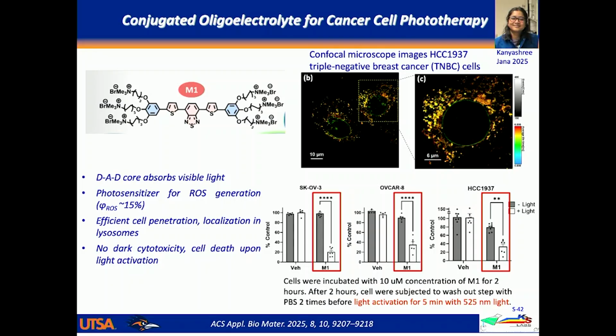So quite clearly the dye does go into the membrane. The different colors represent different lifetimes, by the way. This is a lifetime image. And it turns out green is a little bit of a shorter lifetime than the orange and yellow that we see when the molecule is in the lysosomes. But quite interestingly, if you then take those cancer cells and you expose them to light, just 5 minutes of green light, we can see pretty substantial killing effect. We can reduce the efficacy of the cells by about 80% under the conditions of the experiment that's shown here. These are 3 different cancer cell lines. And so we can reproducibly show cytotoxicity to mammalian cells using this material.